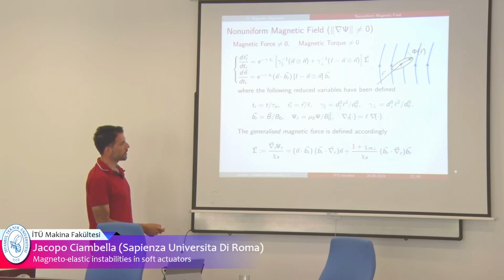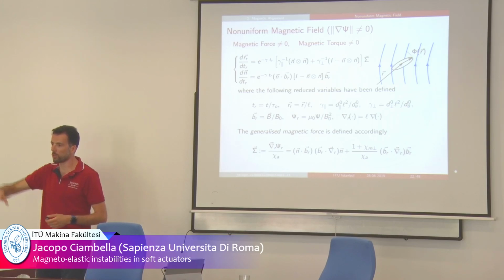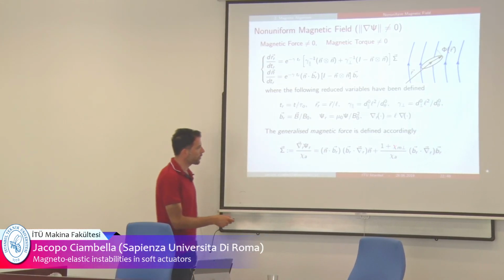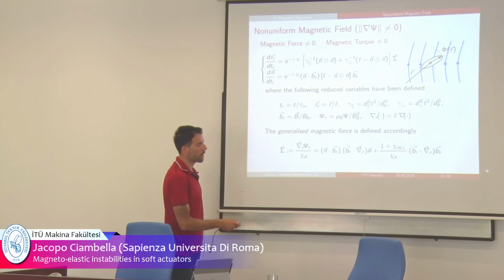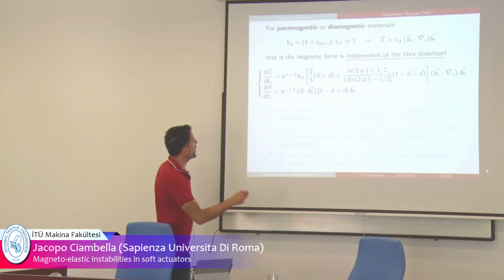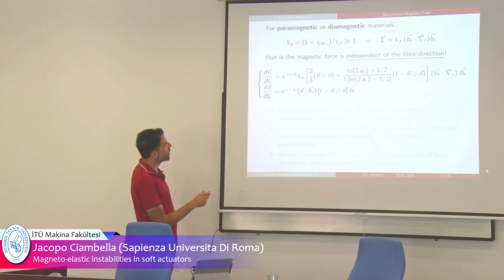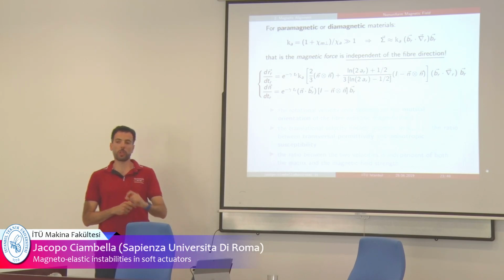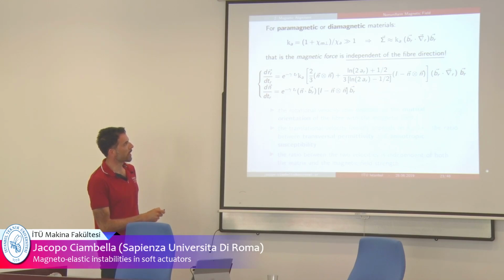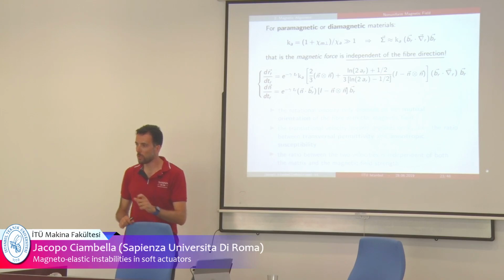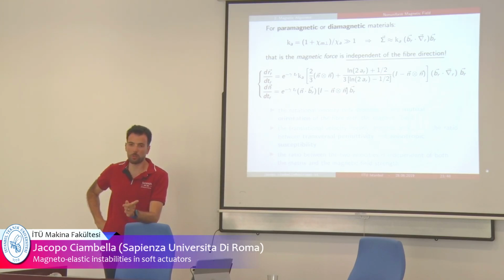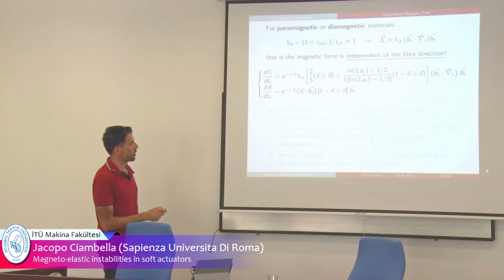One term depends on B_R, the normalized induction field, and on the gradient of B_R, how nonlinear the field is. The other term depends on the gradient of n, so how the orientation of the fibers changes with the plane. Luckily enough, these two coefficients, this is 1 and you have this coefficient here, are drastically different. You can do some approximation of this equation, meaning that if I call this coefficient Ki, normally for paramagnetic or diamagnetic material, Ki is much larger than 1, meaning that the expression of the force becomes this one. So in terms of force, only the gradient of B matters, how nonlinear the field is. It doesn't matter the orientation of the particle. It's an order of magnitude lower, at least. And so you have a simplified expression which is this one.